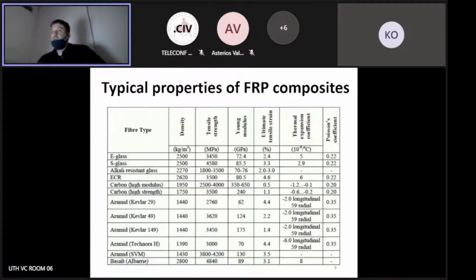So these are some typical properties for FRP composites. As you see, we have different fiber types, and different properties can be observed. As you see, the variability in the tensile strength and the Young modulus is quite high. We can get something from 2,700 MPa in terms of tensile strength up to even 4,000. So if you remember how much structural steel can take, you can see that you can achieve tensile strength even up to 7-8 times that of structural steel.